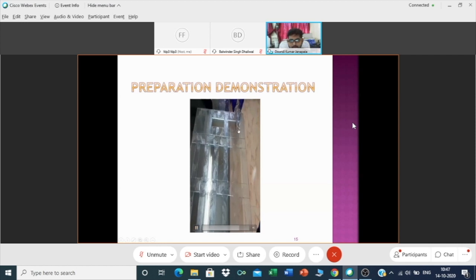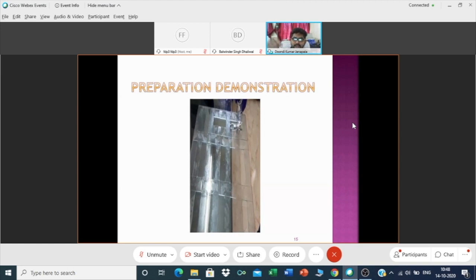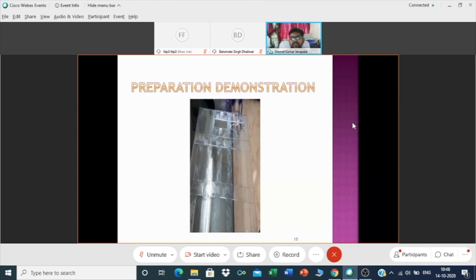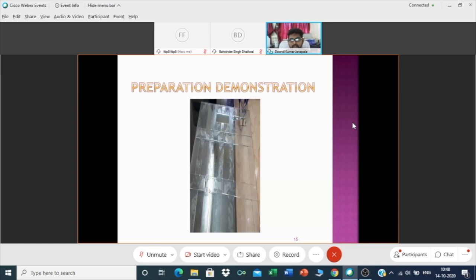So here, while pouring, you can see that I am placing the beaker very, very near to the mold. Why? If you keep a distance between your beaker and the mold, then while it is getting poured, again it will create bubbles. So bubble popping is again a difficult task to do. So you have to be very careful while pouring and make sure that you are not creating bubbles again while pouring. You have to keep it as close as possible and pour evenly.